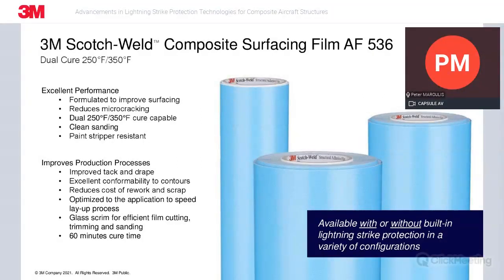So one of the examples of a surfacing film that we use with these conductors is our new AF536. It is a dual cure resin system, 121 Celsius and 177 Celsius, so 250, 350 Fahrenheit, compatible with both fabric and tape systems. We have launched it and made it available with both the traditional expanded copper foils and our newly designed perforated copper foils. The material itself does have a good shop handling property, the appropriate tack, and repositionable during the application. These are great features for operators.